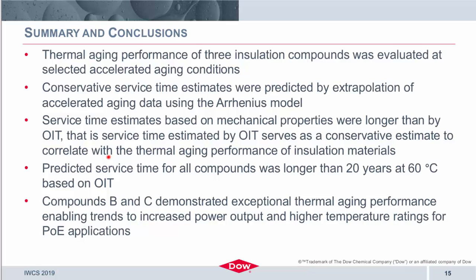So there is room to look at different temperatures if a given or realistic temperature of a given cable or installed bundle is known. You can actually predict then given any temperature. Again, here we just chose the rated conditions. The predicted service time for all these compounds was well beyond 20 years, particularly at the 60-degree Celsius mark, but also even the 75-degree rated mark based on OIT.